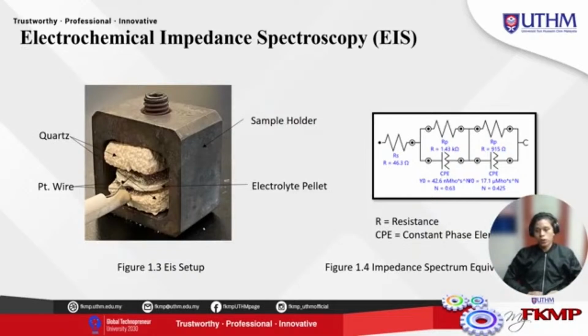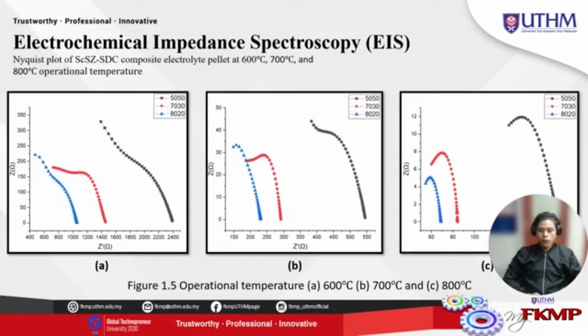Okay, next is electrochemical impedance spectroscopy, which is EIS. The first photo shows the setup before putting it in the furnace for burning at 600, 700 and 800 degrees Celsius. The second photo is the circuit that can give the resistance and CPE value. This is the result for the Nyquist plot of SCSZ composite electrolyte at 600, 700 and 800 degrees Celsius. The trend is the same, where 80-20 is the lowest one, and 50-50 is the highest value.